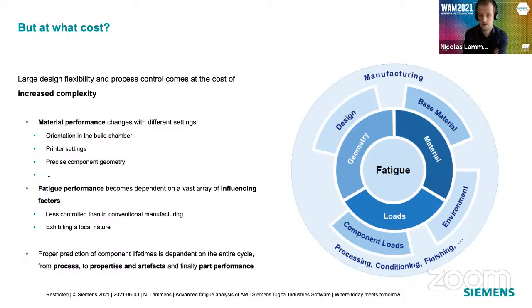Also, if you cannot print the precise geometry, or if you have some features that you have to redesign because of the printing process, the load introduction might be different. And so that means that everything starts to interact with everything, and predicting fatigue life becomes very difficult, even more difficult than for conventional manufacturing. So if we ever want to get to this fatigue prediction, which is accurate and reliable for additive manufacturing, then there's no way around it. We have to account for the process first, so for the manufacturing step. And based on that process, we have to predict the properties and the artifacts that you will get. And once you know those, you need a material model that is able to account for the effect of all those properties, and that can finally tell you what the performance is of your component.